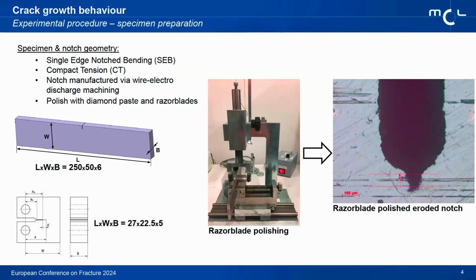To investigate this behavior, we manufactured two types of specimen: a single-edge notch bending specimen with quite big dimensions, and a CT, a compact tension specimen. In both specimens, the notch was introduced via electro discharge machining. Afterwards, to receive a really sharp notch, we use a self-built razor blade polishing machine, where we coated the razor blade with a diamond paste and drew the razor blade several times over the notch root, and finally receive a really sharp notch.